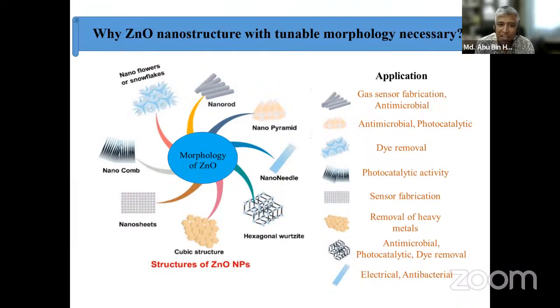And for photocatalytic activity, you could use nanocomb. For sensor fabrication, we are finding applications from nanosheets, and for removal of heavy metals, cubic structures were very important. And as usual, the hexagonal wurtzite structure showed antimicrobial, photocatalytic, and dye removal activities. And nanoneedles showed electrical and antibacterial properties. So we can see that the application is dependent on morphology. The application is very versatile, very wide.